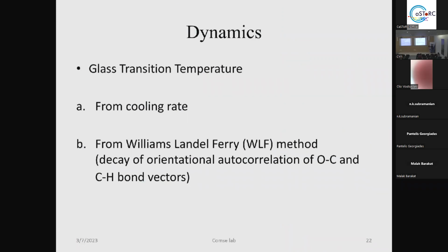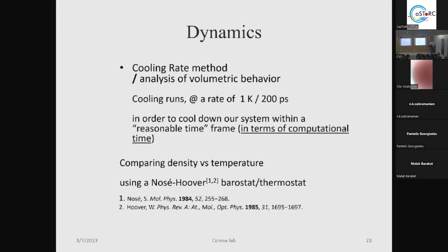Also, we saw the dynamics of this epoxy network in two different ways, with the cooling rate and with the WLF method, taking into account the correlation functions of the vectors. The cooling rate method that we did was to cool the system at 1 Kelvin per 200 picoseconds, which is of course a brute force method compared to the experimental way that people do in their laboratory, about 1 or 10 Kelvin per minute. But people who do simulations know that these experimental rates are very, very slow, and we weren't able to see that.